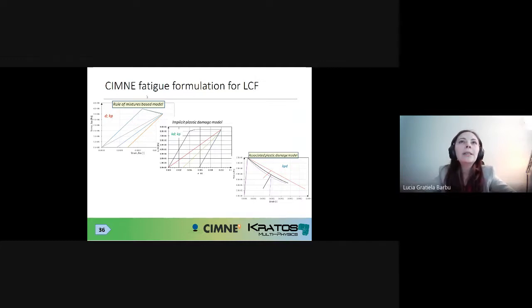For instance, the implicit plastic damage model of Viviana had a normalized damage dissipation and a normalized plastic dissipation. These were the internal variables of the model. And for the associative plastic damage model, we have a sole unique dissipation, which quantifies both damage and plasticity dissipation together inside this specific value.